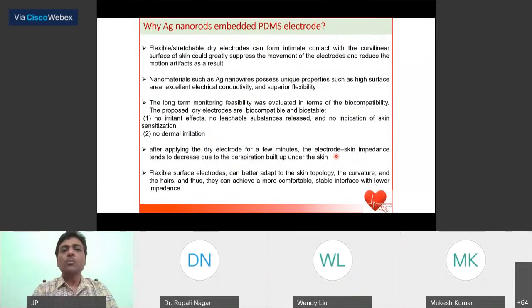So now the point is, what is the advantage of these silver nanorod embedded PDMS ECG electrodes over the conventional electrodes? One of the things is that these electrodes which we fabricate are flexible and stretchable, and we have also measured the mechanical properties. They are mechanically robust because these nanostructures inside the PDMS matrix get fixed there. And you can reuse them. We have also done a peel test, so you can reuse them, and they are fit for long-term heart monitoring, which was not currently available with conventional electrodes.